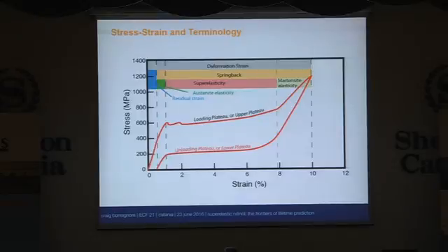Some terms are confusing because they aren't super standardized, and when we say things, we often kind of confuse each other. So we try to use these terms, but just to walk you through the basics. The main thing is as we load the material, we're on this upper, what we call the upper plateau here, in terms of stress-strain relationship, and we can endure something like 6 to 8% strain while we're transforming. Once the transformation is fully exhausted, we get into a martensitic phase, and eventually, if we kept going, this would fail like any other material.